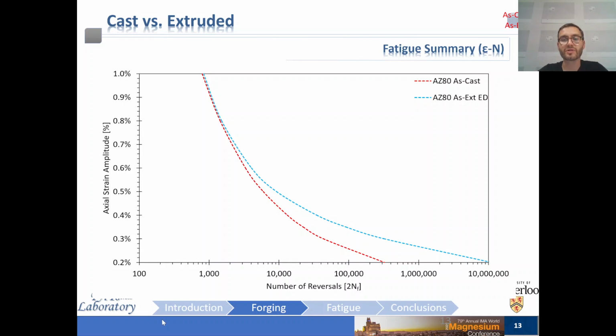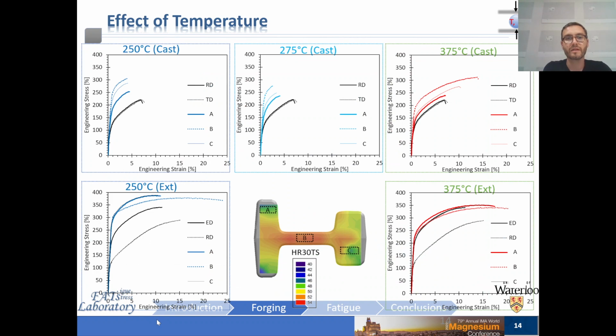Now extending this comparison towards the fatigue performance of cast and extruded magnesium alloy, as one might expect, there once again is a dramatic difference between the two, which is deeply rooted in these contrasting microstructures and different textures, leading to vastly different cyclic responses. It can be observed here that under strain control fatigue testing in the high cycle regime, for a given strain amplitude, the extruded material has a life which is superior to the as cast material by pretty much more than an order of magnitude, which is obviously a very significant improvement.